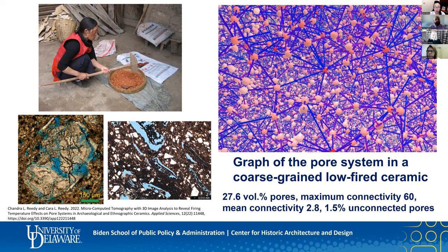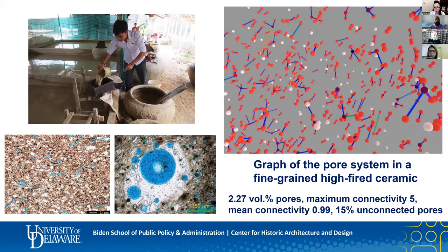In contrast, when the raw materials are more finely ground and sieved and perhaps levigated in water to remove more of the large impurities, as we see being done on the upper left here, have finely ground additives, and firing is done at high temperatures and sometimes for long periods of time, more of the grains will completely melt and vitrify, and a dense glassy matrix forms, filling in and breaking up many of the previously connected pores and then forming new round isolated pores as gas bubbles get released during vitrification, as we see in the thin sections